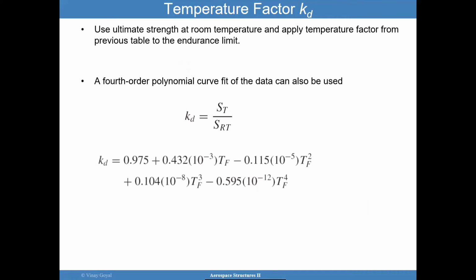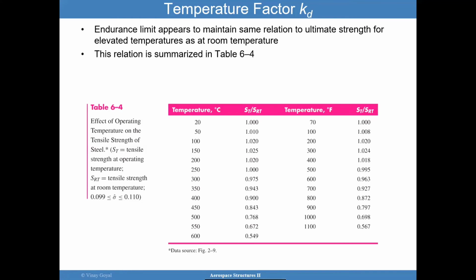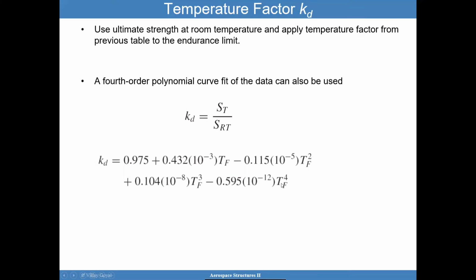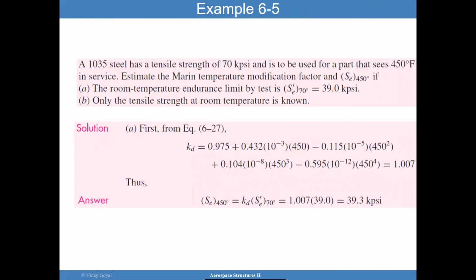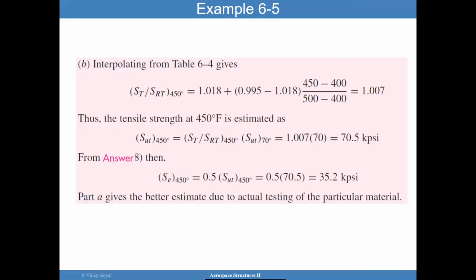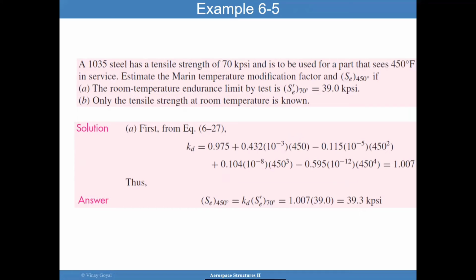And here is a formula for it. You can use either this or the interpolation curves. But if you were to plot this, you can get this curve fit and then use that. And here's yet another example. If you have a steel at 70 KSI and it's going to see 450 degrees F, quickly plug it in and get a KD of almost 1, basically no effect. So then for your actual application at 450 degrees F, the endurance limit is mildly affected. And that's just using interpolation, but you will get the same value as this approach.